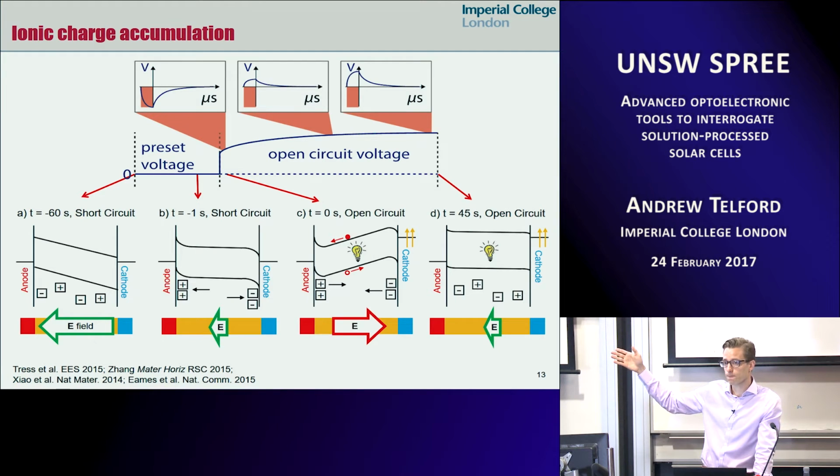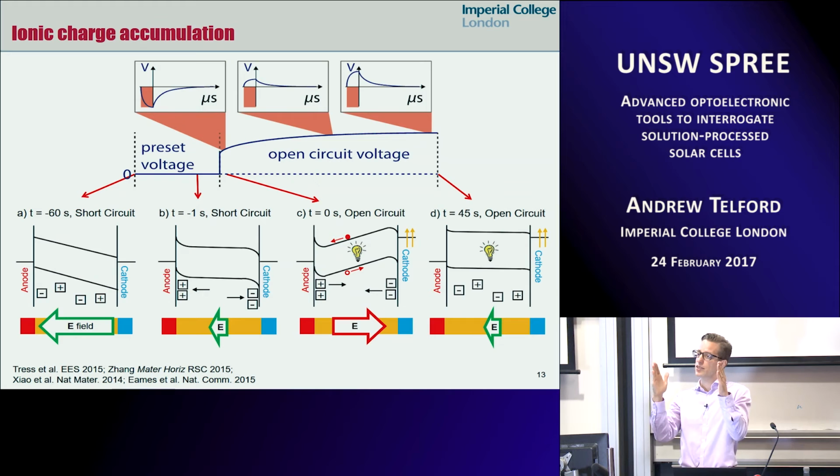This means that you have an internal electric field in the device that is pointing towards the left of the slide. Now, if this is true and you do have ions that are able to migrate in the bulk of the material, then they will likely accumulate at the interfaces, create an opposite electric field, thus flattening the band throughout most of the thickness of the material.